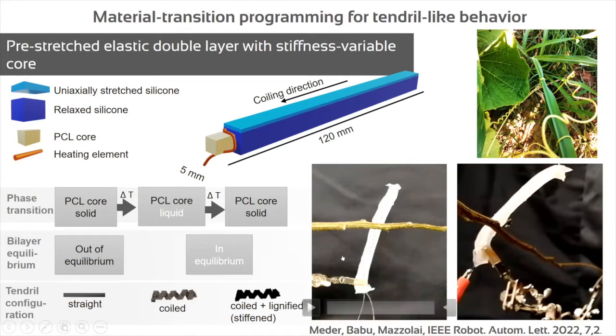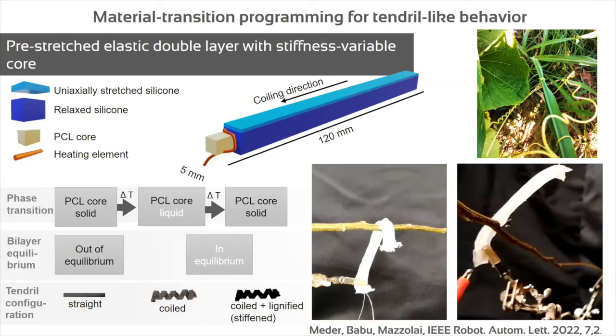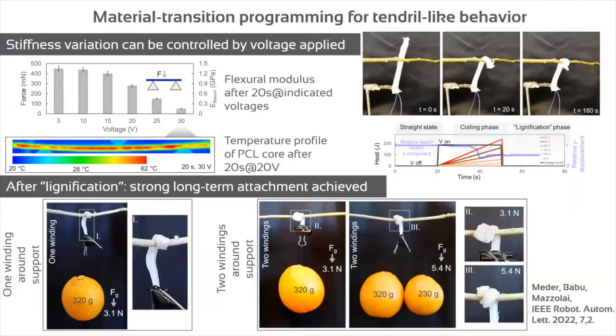As I mentioned, we obtain this coiling depending on the angle of the fiber inside the system. And when we stop heating, the PCL becomes solid again, and what we obtain is a sort of lignification, like in the natural tendril. So what we obtain is an increase of the stiffness. In the natural tendril, this is obtained by a change in the material.